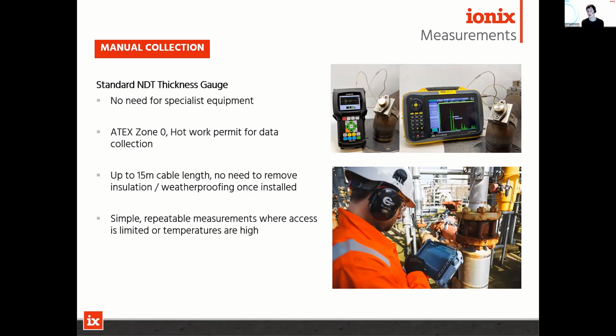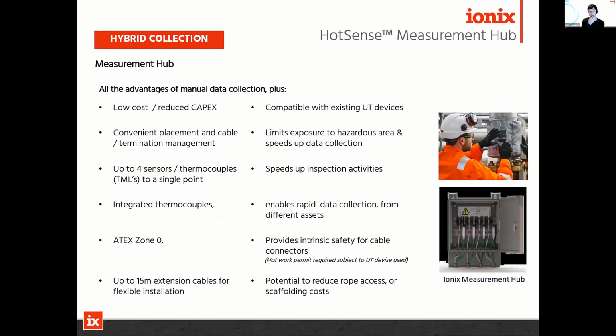The advantage of installing one of these probes, compared to the inspection probe, is that with a fixed probe like this, you get much better trending of data, using the same probe in the same location, and the same piece of equipment and procedure to collect measurements from it each time. So it's much easier to get trending data for wall loss. It also means that you can install the probe in an inaccessible location, in a hazardous high temperature location, and run the cable, up to 15 meters, to an easy to access location for data collection.